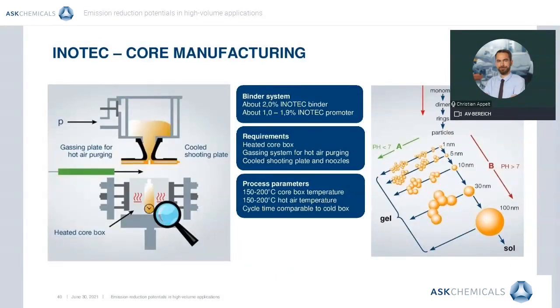A typical molding mixture based on silica new sand is composed of approximately 2% of the liquid Inotec binder and 1.0 to 1.9% of the solid Inotec promoter. The higher the addition rate of the promoter, the higher the performance level of the product.